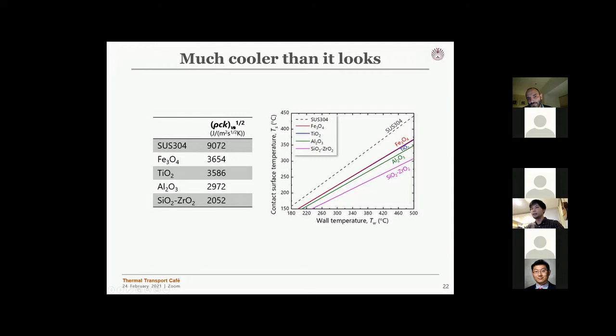Okay, so if you have rather high thermal property parameters, we don't have much gap between those two. If you take 420 degrees Celsius of wall temperature, the contact surface temperature will be somewhere around 300, yeah, just below 400.